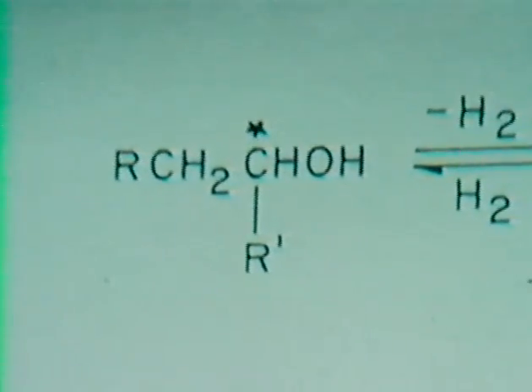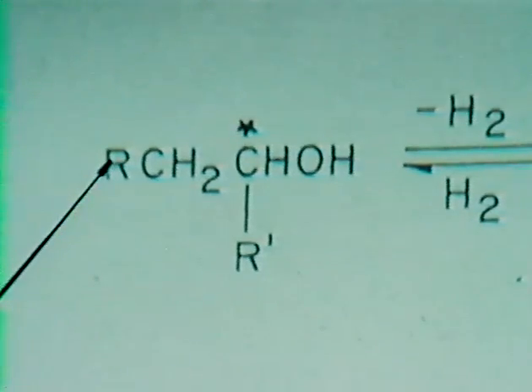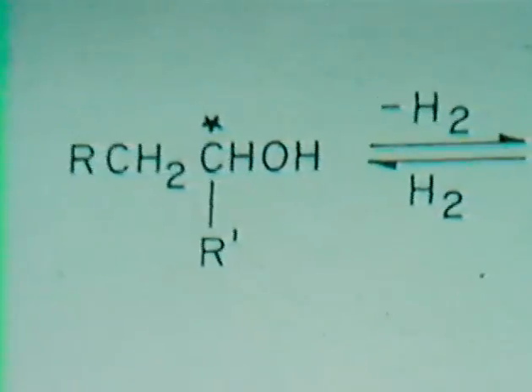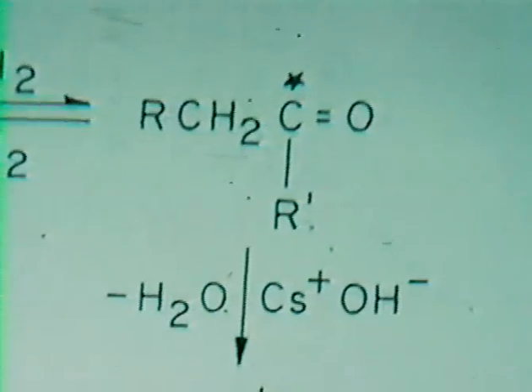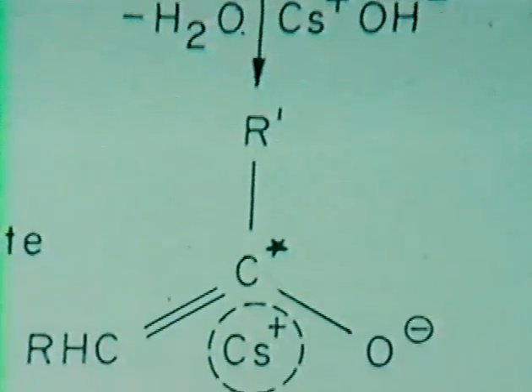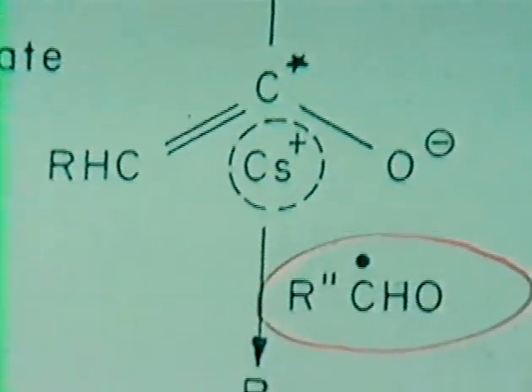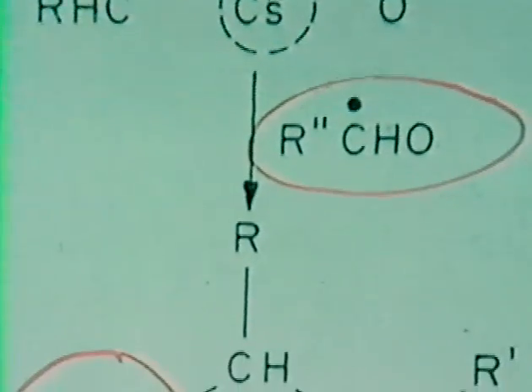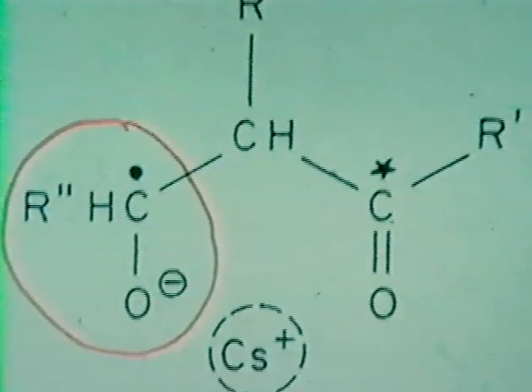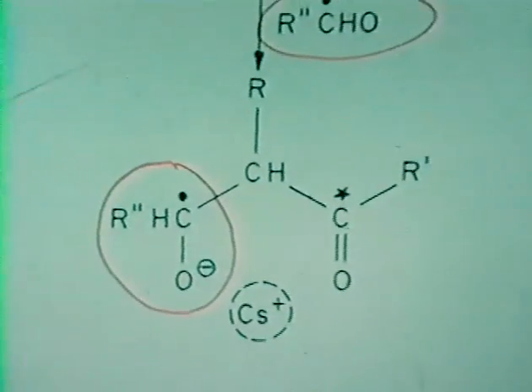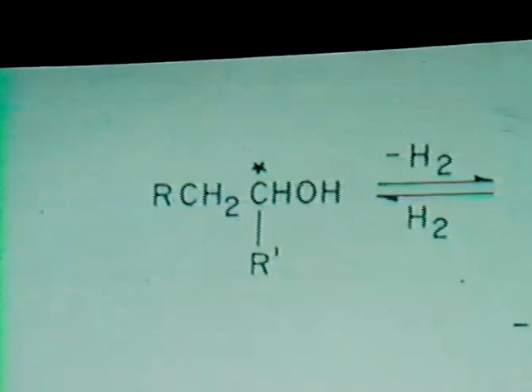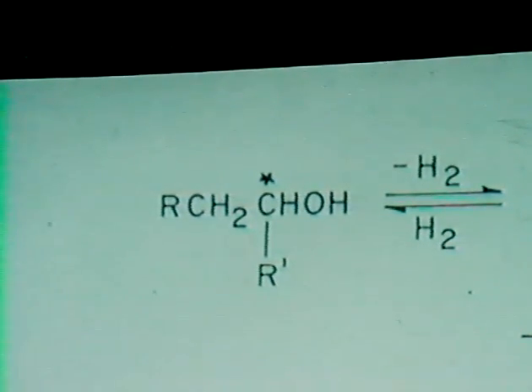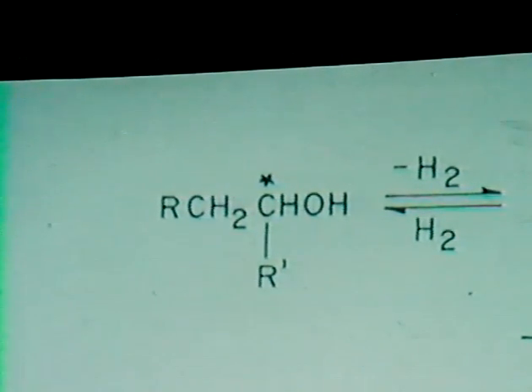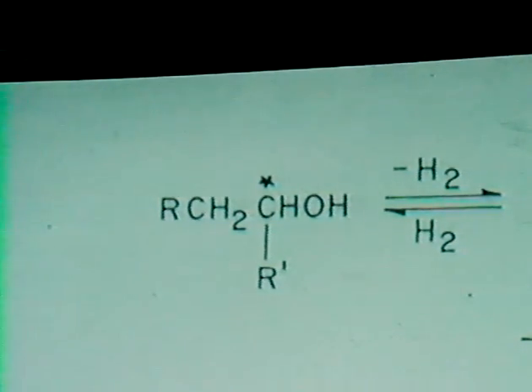There are three types of groups here, labeled R, R double prime, and R prime, which are added. This would be a synthesis in which I am adding this kind of alcohol. If R prime is hydrogen, this is a primary alcohol. If R prime is a CH3 group or other alkyl group, then it's a secondary alcohol. I can inject secondary alcohols into this synthesis, even though the synthesis does not produce secondary alcohol. I can make new products from these secondary alcohols.